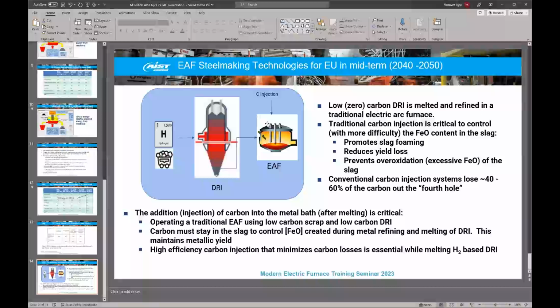The disadvantage is trying to make sure that at the same time you're balancing your fluxes and your carbon inputs. If you put in generally a lower grade scrap, it'll come along with, I'm going to call it more dirt or more silica, more acids that will end up in your slag that you have to balance using things like lime and dolomite in order to try and protect the refractories in your furnace, in order to make a foamy slag, to make sure that you're getting the phosphorus out of your steel,